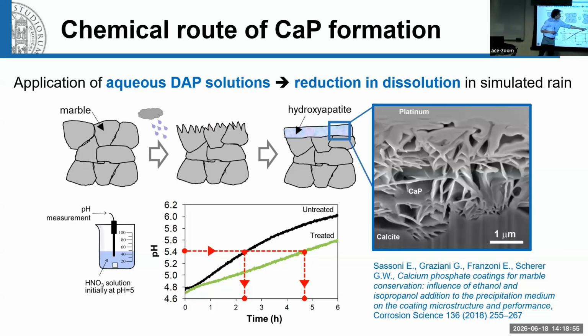So here, for the untreated marble, you see this progressive increase in pH over time. My goal is, ideally, to have a flat curve, because it means that my protective layer is acting as a barrier, preventing the dissolution of the stone. So here you see there is a decrease in the curve. For instance, the same level of pH is reached after a time that is twice as much. So I can think I have extended the lifetime of my model. However, this curve is not flat yet.